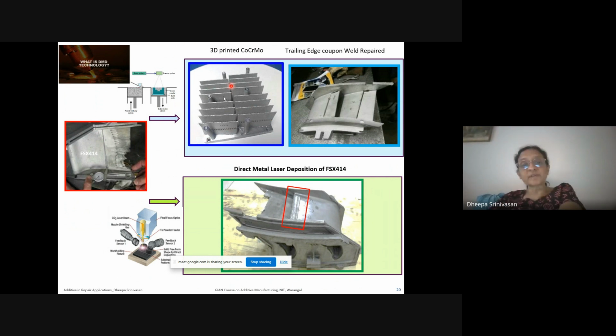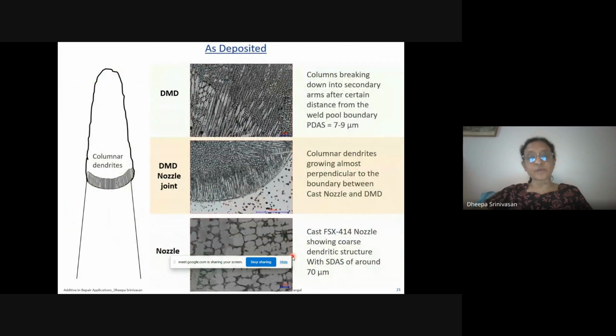The top part is what we completed and I shared with you, and these are the welded parts. What we also did, shared with you right at the beginning for the same example, is we tried in parallel using direct energy deposition and directly coating on this, adjusting the fixture and so on, so that you directly cut the damaged part and build it using direct energy deposition. With that also we had a success story. It was not bad at all. Again, this is part of Kaustub's work, published in his MTech thesis.